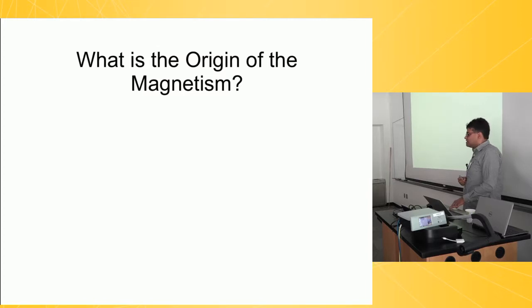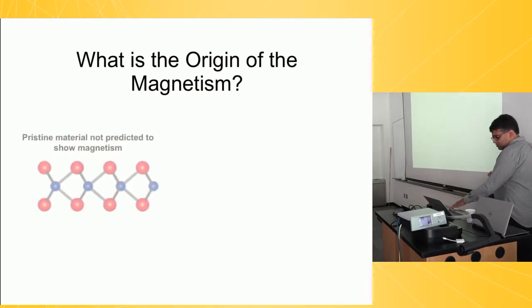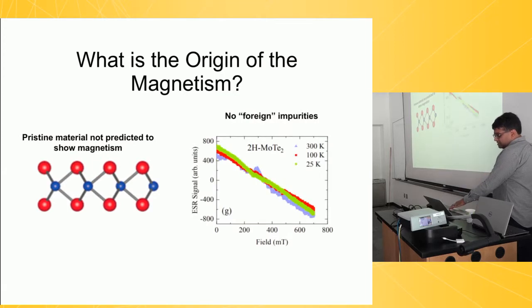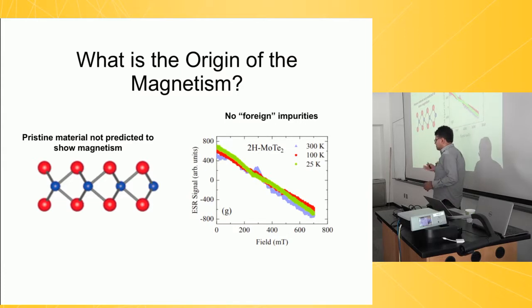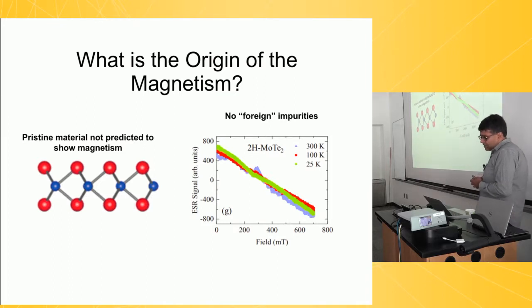OK, so now the question is, why are these things magnetic? They should not be magnetic according to the pristine material. One thing you might imagine is that you have some foreign junk in there. Transition metals, they might have iron or chromium or nickel, things that are magnetic. We've looked quite carefully with lots of different techniques, and there isn't anything there. And there isn't anything that can explain 40% of the sample being magnetic. Just no way.